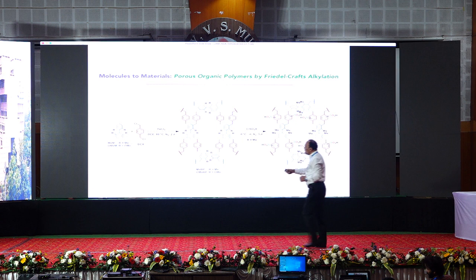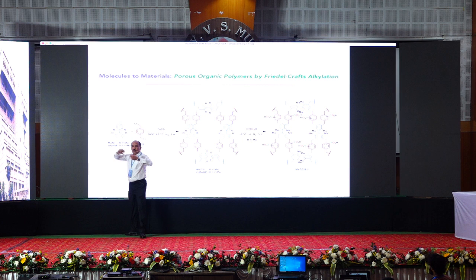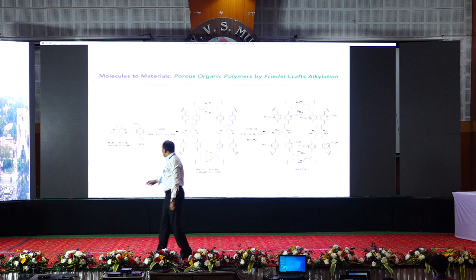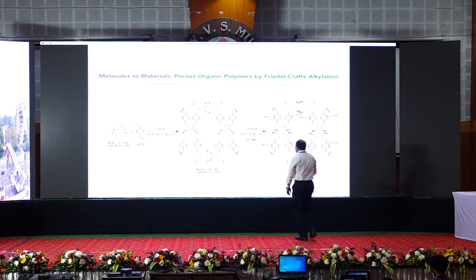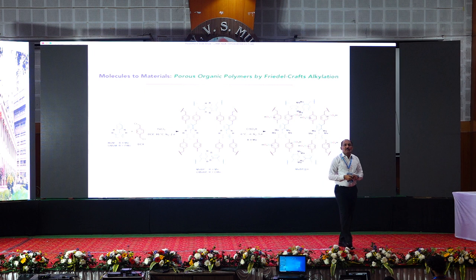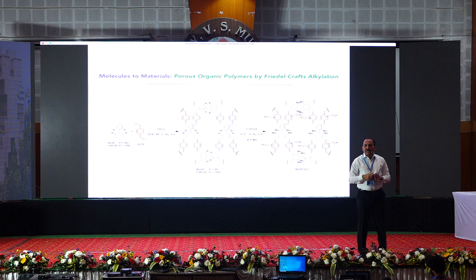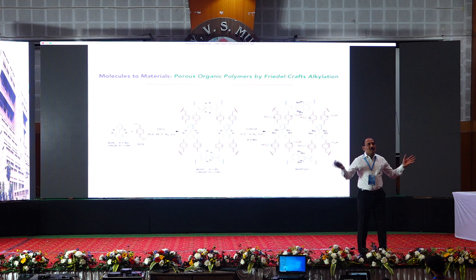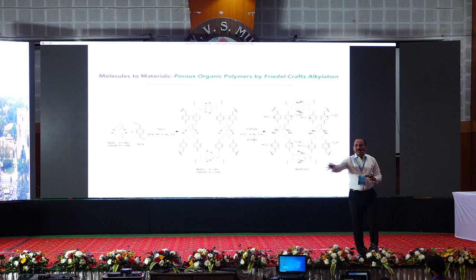So take a very twisted molecular building block, like biphenyl with methyl and methoxy at the ortho positions. You twist it up, the molecule is inherently twisted, and now you polymerize, and such a material is inherently porous. Now, on this material, I can do a simple chlorosulfonation and introduce sulfonic acid. It's basically an acid. I have a polymer. I don't need to use n number of chemical transformations. Now I have a very strong acid as part of the polymer that is insoluble, so I can put it into the reaction medium as an insoluble material.